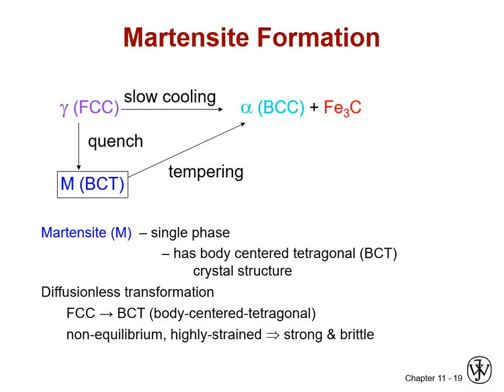If we give that tempered martensitic structure longer time at temperature, eventually the carbides we form, the cementite we form, will ball up and we'll end up with a spheroidized structure, which again is not as strong as tempered martensite that hasn't been held at its tempering temperature quite as long, but is very, very tough. So you can think of spheroidized steel as being a long duration extension of tempered martensite, because that's what it starts with.